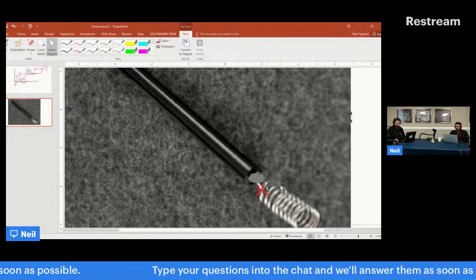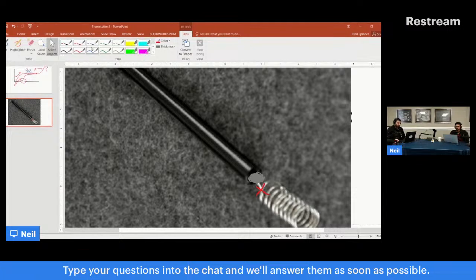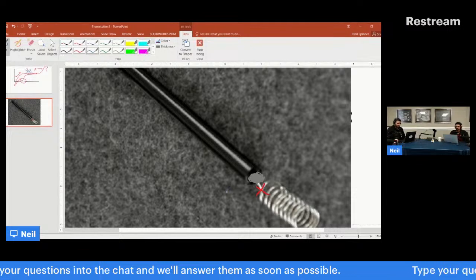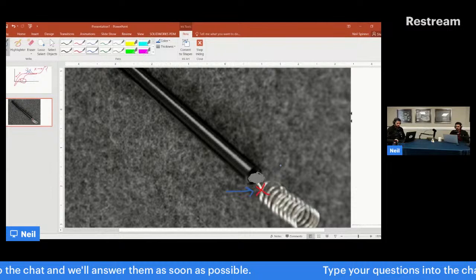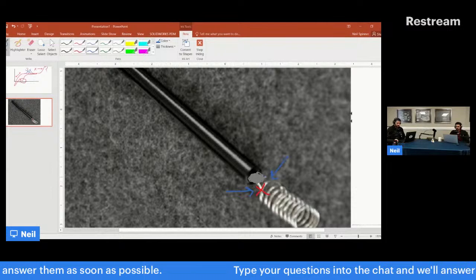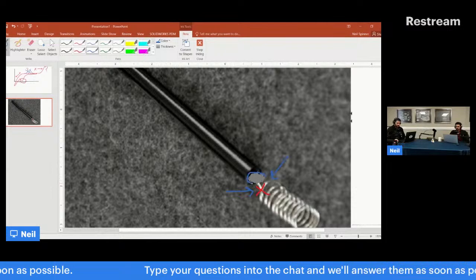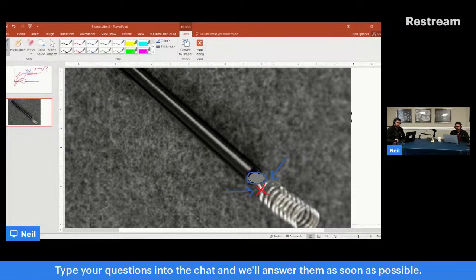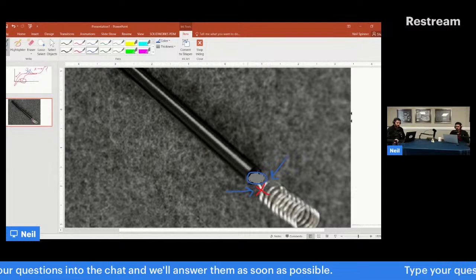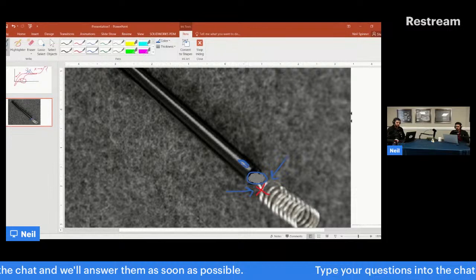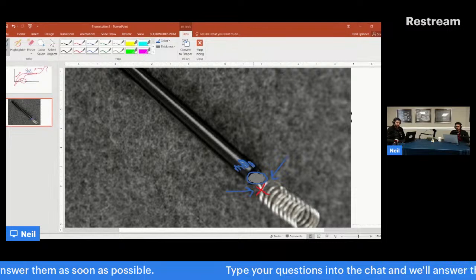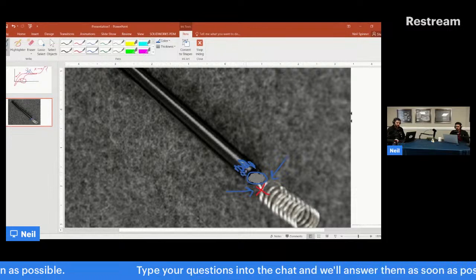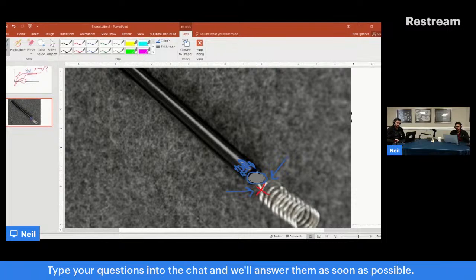To try to do any kind of a solder, unfortunately, would involve heat, and you would most likely compromise this seal around this plug, this Teflon plug. And this body here, this blue, it's like an epoxy tube that could also melt. It could compromise the seal.